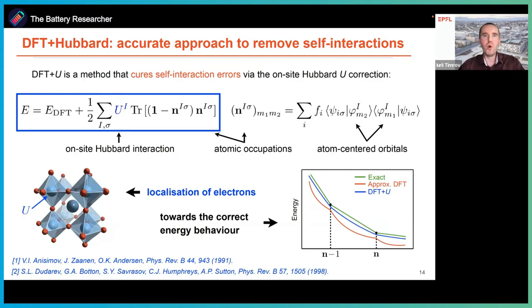There are many methods, but in my talk, I'm going to focus on one of them, the so-called DFT plus Hubbard. The main idea is highlighted in this blue rectangle. The total energy of the system E is equal to the total energy obtained from approximate DFT, E_DFT, plus some corrective terms. This term is shown here. It's 1/2 sum over atoms labeled I and spin sigma. U of I is the really critical parameter, which is called the onsite Hubbard interaction parameter.